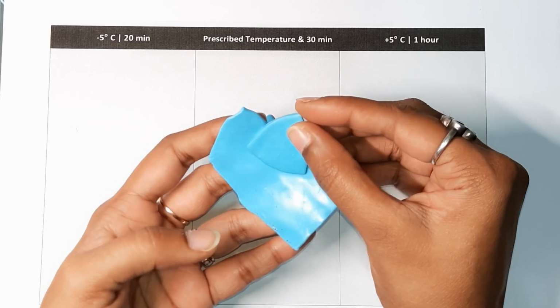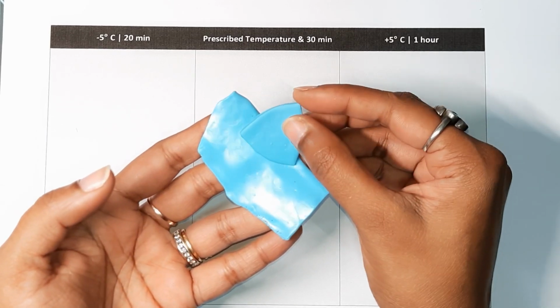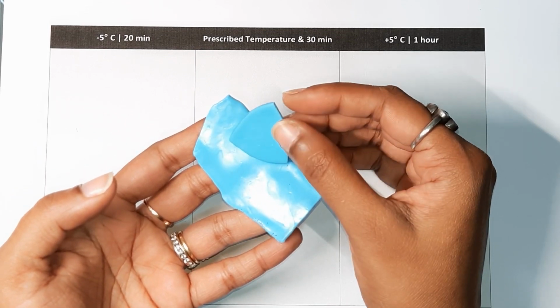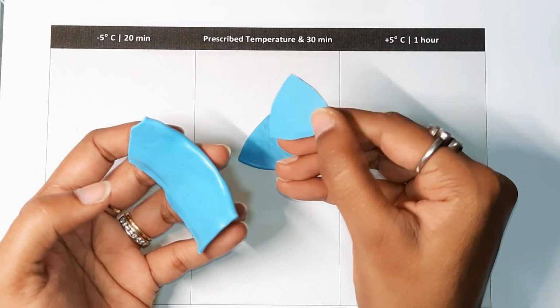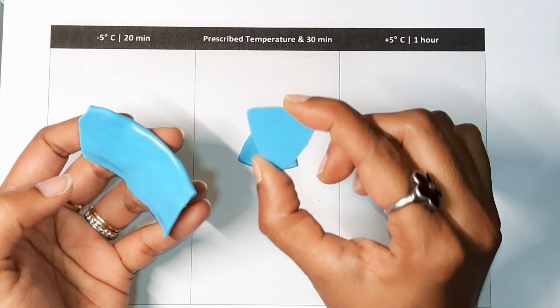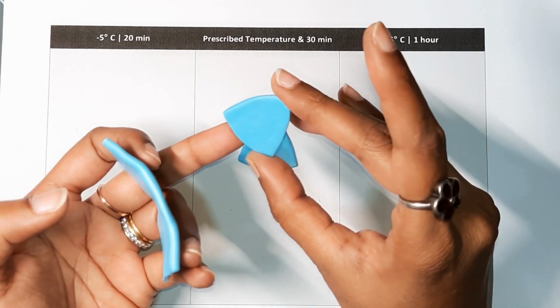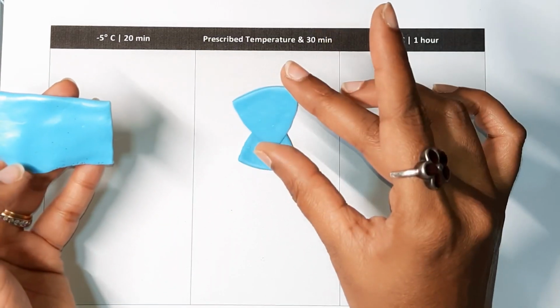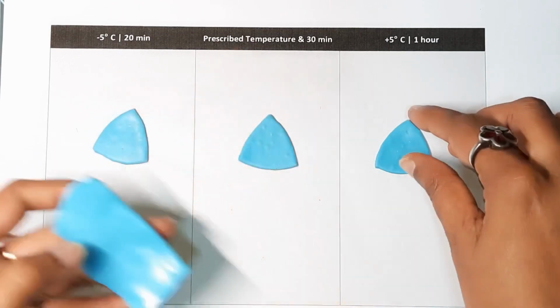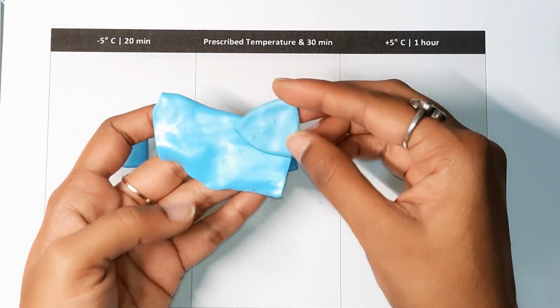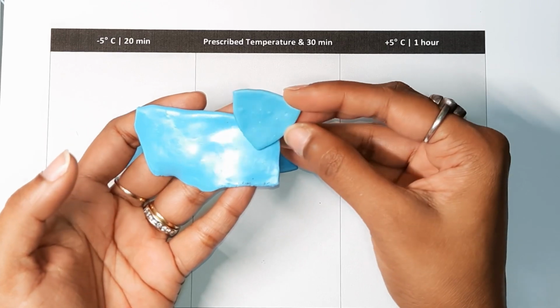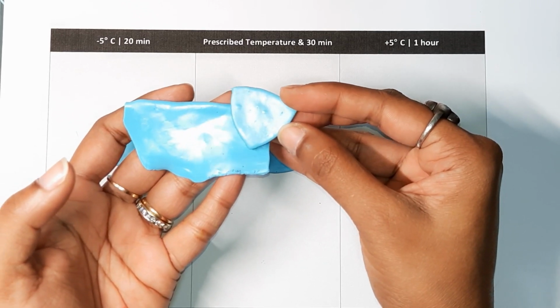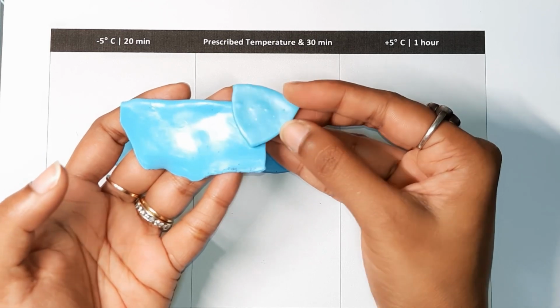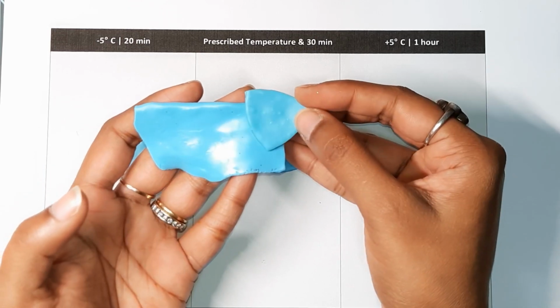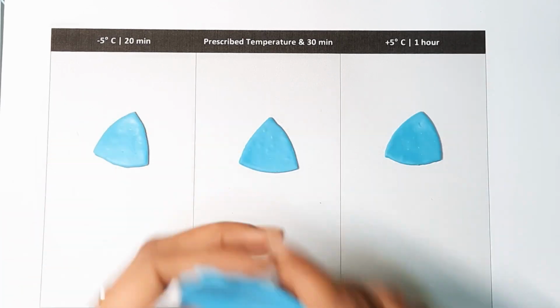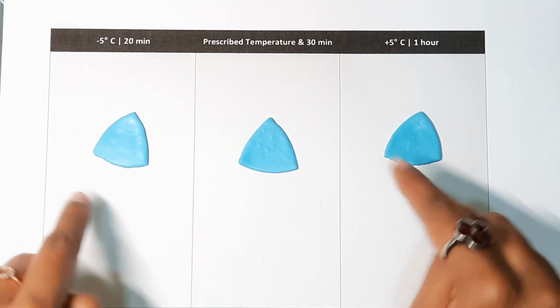I wasn't expecting this version to have any color variation, because it's below the prescribed temperature. It's very true to the original color and opacity, but lots of bubbles on the surface. So that is disheartening, but the color change is absolutely non-existent. And if I baked it at 5 degrees higher than the prescribed, there is a color variation. It has burned on a very light level. You see a slight yellowing or browning of the color, so there is a difference in the color. Again, there has been bubbling in all 3 pieces.